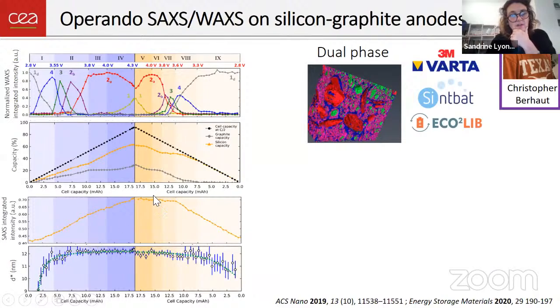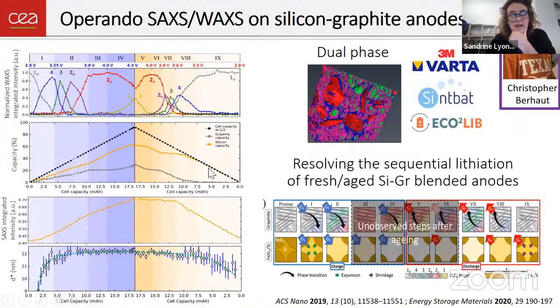And you put all these results together and you get this, that is the contribution of each of the phases to the total capacity of the battery, which is exactly what we were looking for. And at the end, with all this data, you can resolve the sequential lithiation of your anodes in a real battery that is having a good electrochemical behavior. And we could do that on aged batteries. So batteries we were cycling in the lab for hundreds of cycles, and we put in the beam at the ESRF, and we understood what happens in the aged batteries, which is basically that some of the steps in this mechanism are skipped and are not observed anymore. And this is causing some degradation of the performance of the battery.